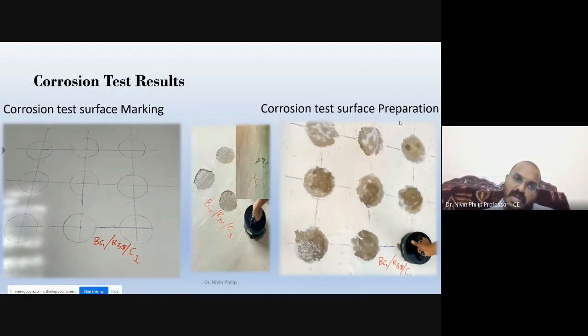So we made a grid of 9 by 9 and we removed the cover concrete, plastering and paint in that portion. Then we tested at that point, both in the x direction and y direction. The x direction and y direction mean, in the slab, the long span reinforcement and the short span reinforcement. And we obtained a value which is called corrosion rate. Corrosion rate is different from corrosion potential. In corrosion rate, we get a wonderful contour.